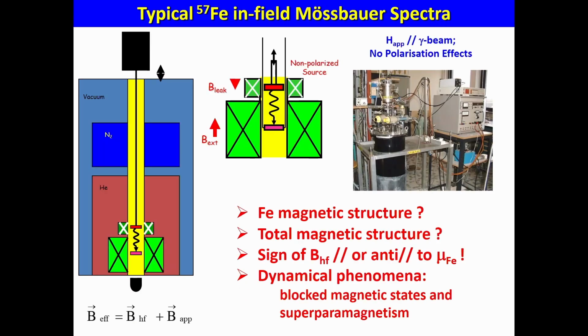So, of course, if you use an external magnetic field, you can obtain such a result. It's not possible to conclude from a sextet that it's ferromagnetic. And there are a lot of papers saying, my sample is ferromagnetic because I have a sextet. No. There is a magnetic order of iron. Ferro, antiferro, it would be the same spectrum. You are not able to tell. But if you apply an external field, you can.